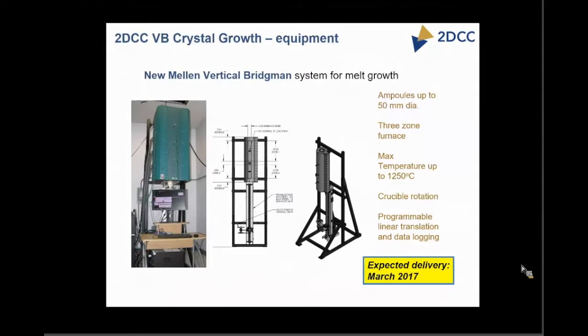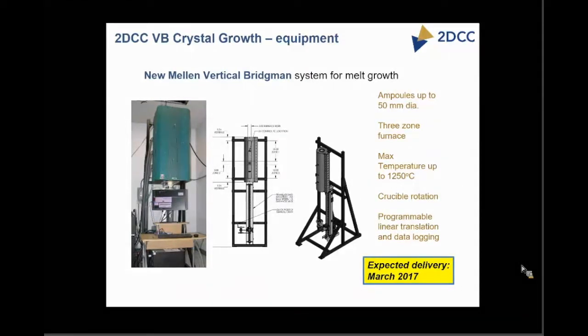So a key part of the equipment that's being set up at the 2DCC is a new vertical Bridgman system for melt growth. The vendor for this system is Mellen, and there's a couple of schematics of the system shown here. So this has been designed and specified to be able to do relatively large areas. So we can go up to 50 millimeter diameter, and we can configure this to go down to smaller sizes, down to 5 millimeter diameter crystals. So it gives us a wide range of flexibility in terms of the size.